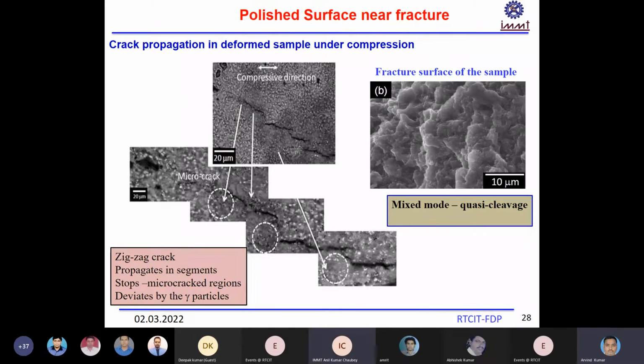So what is the actual reason why we are getting such a strength of twice or thrice of this cast structure? The fracture surface was also analyzed, and in the parent material after fracture, you can see how the cracks are going and stop here, and then other cracks form and stop here. So it's not that one crack goes throughout from one portion to the other portion, but it is stopped by certain micro cracks at the tip of the main crack. So the cracks are stopped, and then other cracks are forming. So it is a delayed cracking. So that's why in this material you are getting ductility as well as strength in this condition.